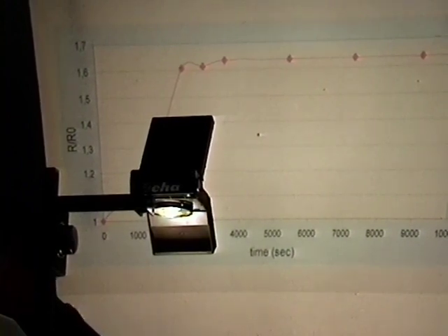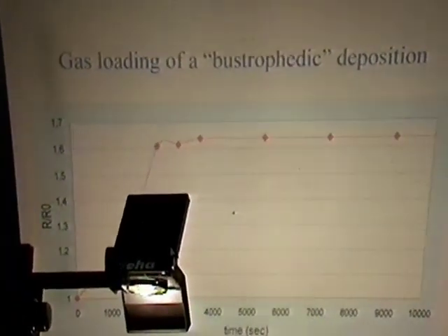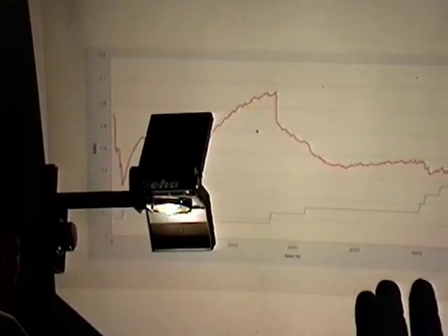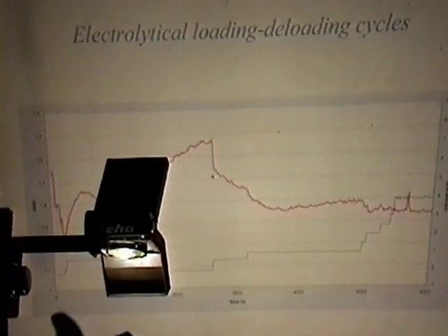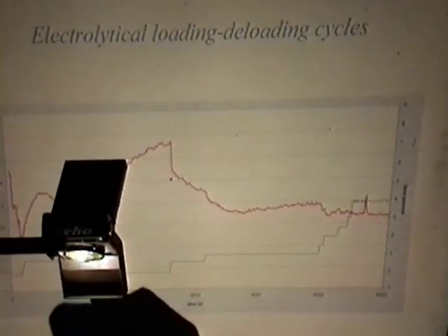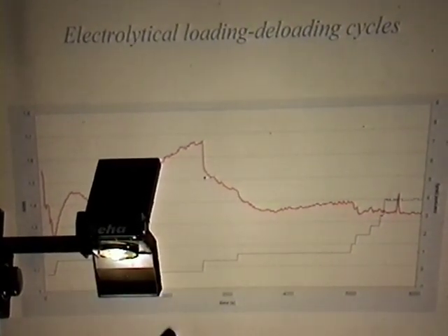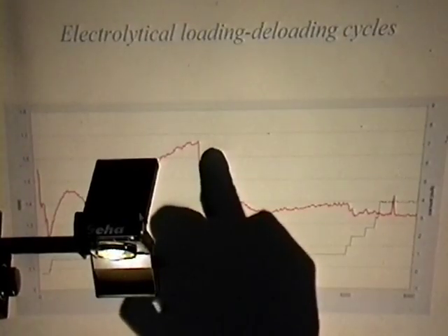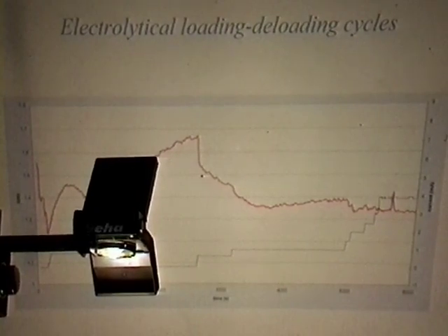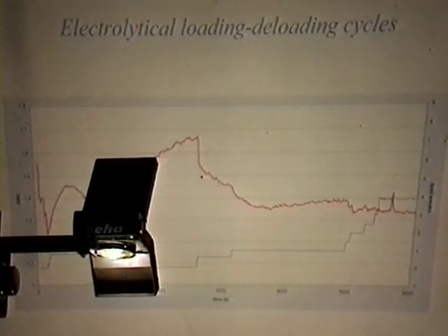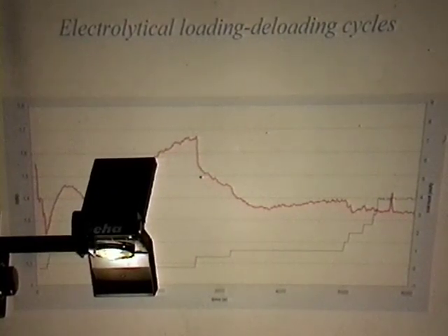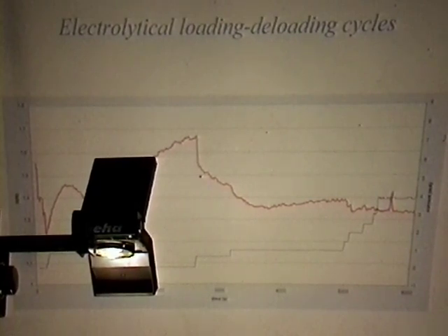If we try to do a gas loading of the deposition in 1 bar of deuterium, we obtain this maximum here. Again, we are lower than the Baranowski curve. If we put the same sample in the electrolytic cell, we see a very quick crossing over a maximum, but the maximum is very small. If you switch off the current, there is a deload. This feature means that we have really reached the right side of the Baranowski curve. So we are in a region of very high loading, but we are not able to give a qualitative explanation to this behavior.